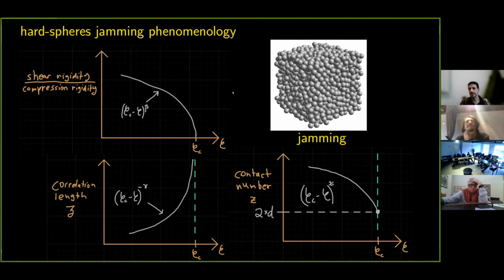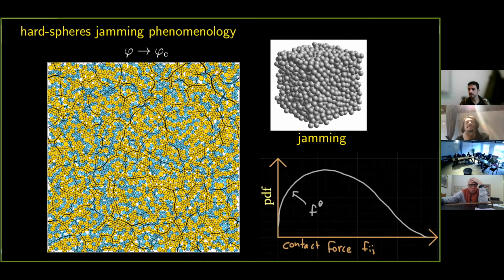On top of that, if you consider the properties of the critical state that you reach by taking this hard sphere packing and just compressing it until you cannot compress it further, then if you look at the statistics of the forces between these particles, they are described by a distribution that grows as f to the theta, with theta some non-trivial exponent. So this is in a nutshell the phenomenology of jamming.